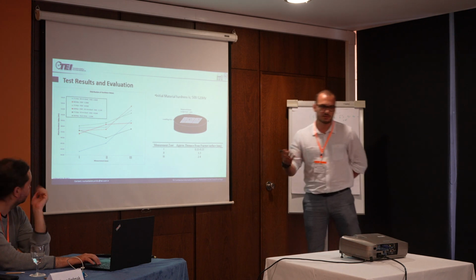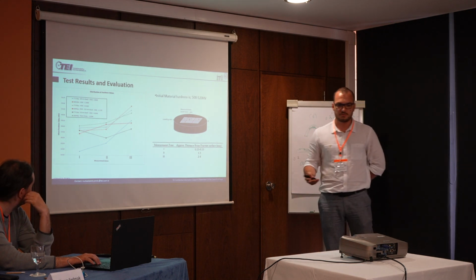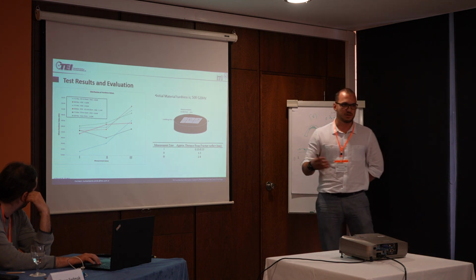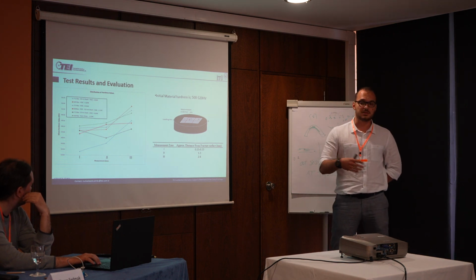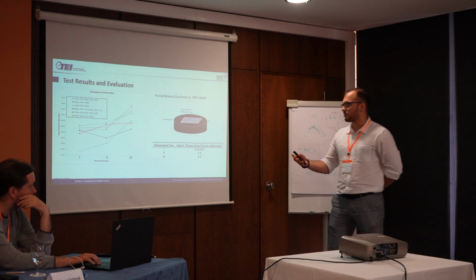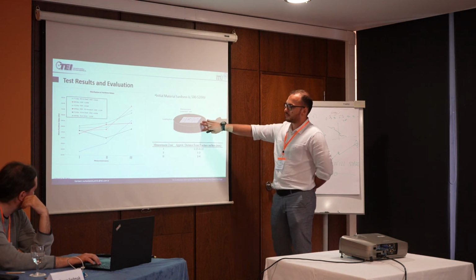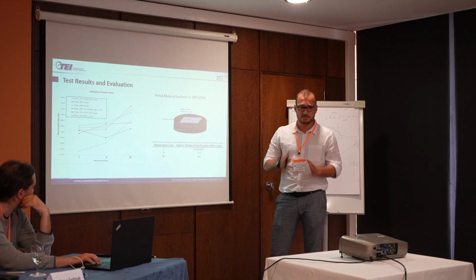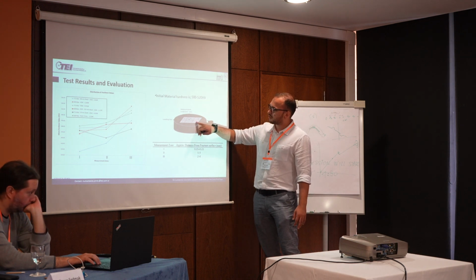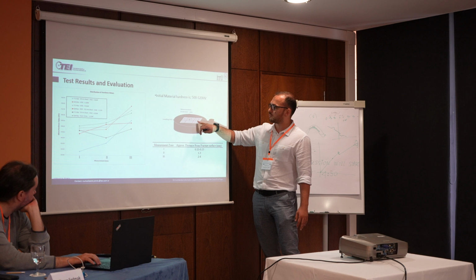We can move on. In order to understand why this may have happened, we first performed a hardness test in order to understand if the material is softened or hardened or if something different happened. To do that, we prepared our fractured specimens and measured hardness values from 3 different regions.